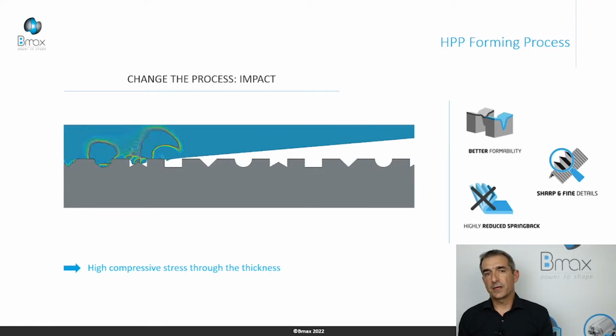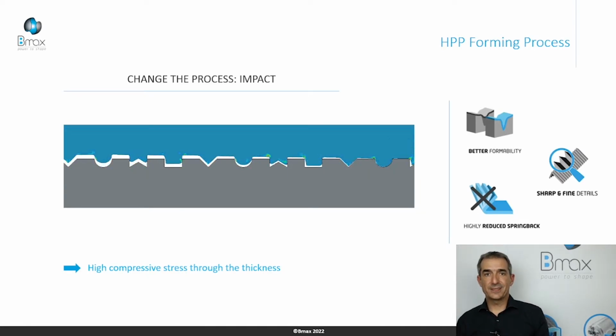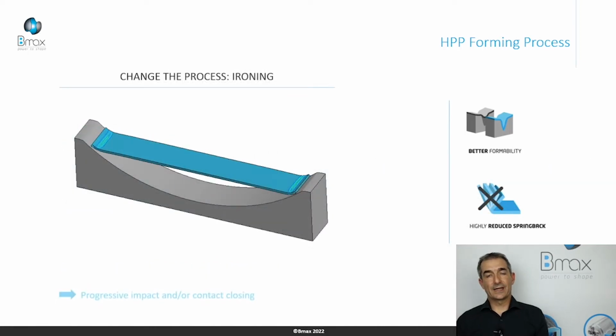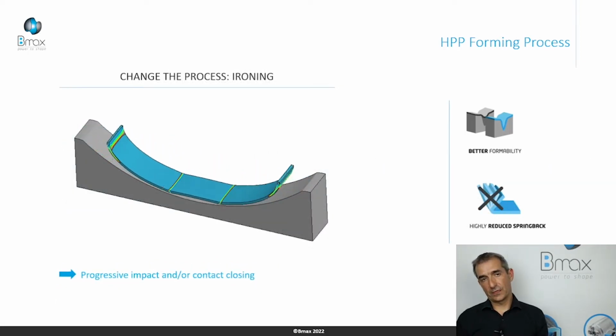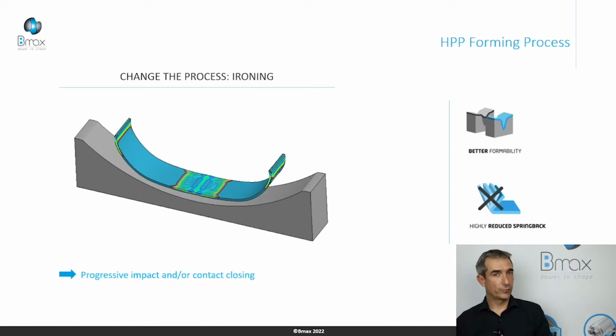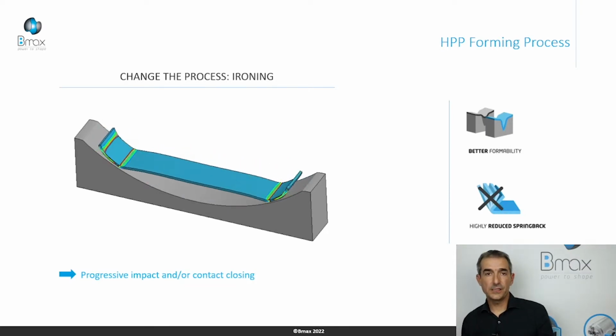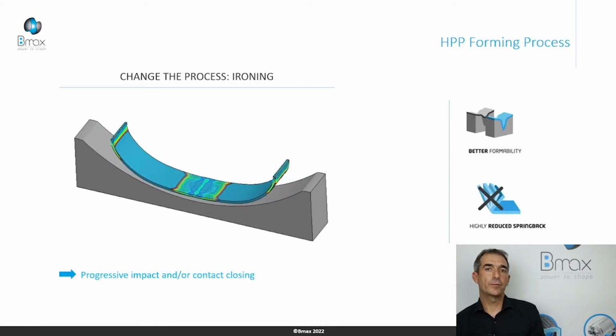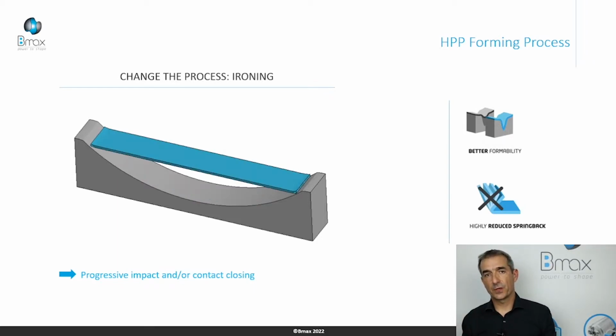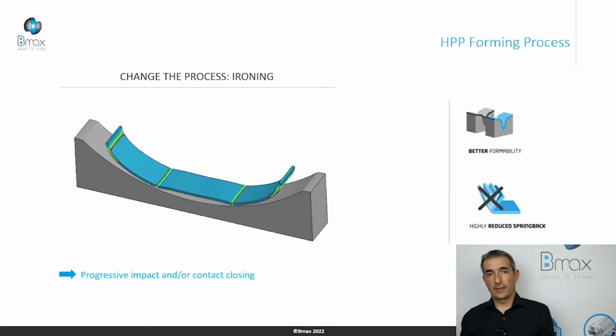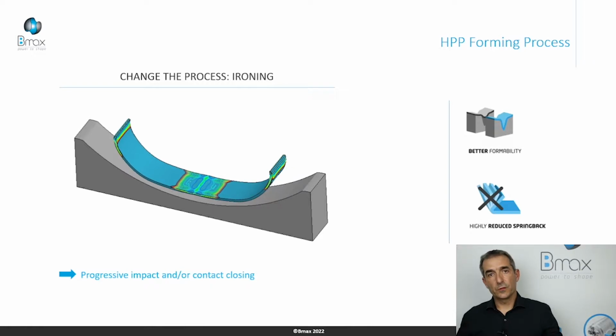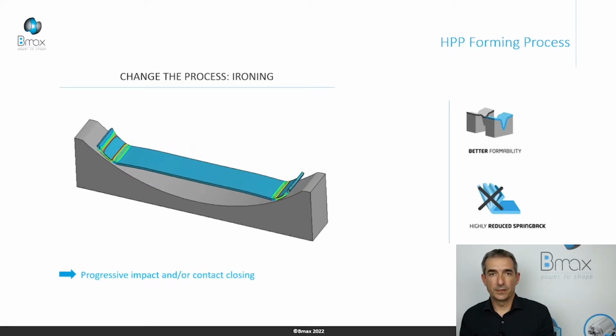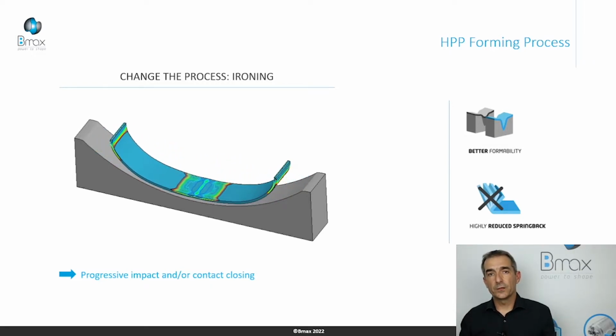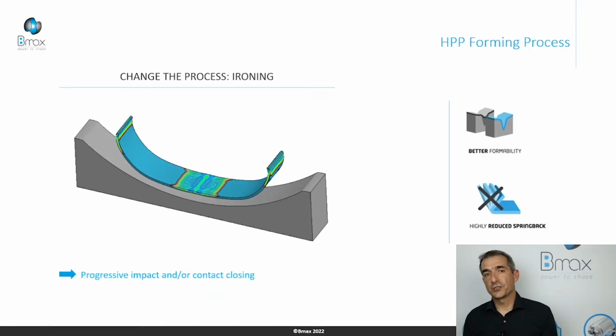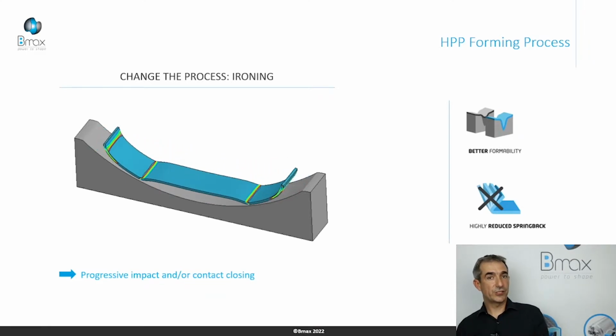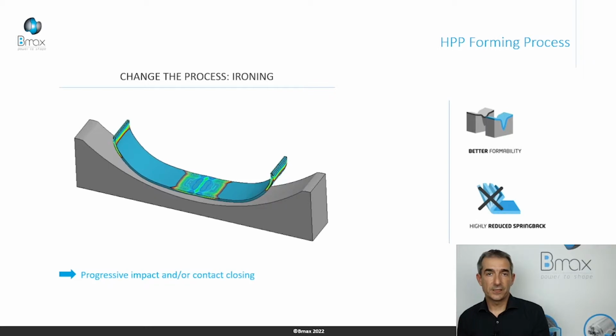But this impact is not constant in time and in space, as usual. So we can have an ironing. Ironing is a progressive contact closing, a progressive impact in a dynamic process. In this example, we have a first impact on the side of the blank, and this contact closing comes from the side to the middle of the blank. In this way, we push the material in the middle of the blank, and we can change the thickness distribution. In this way, we change the formability of the materials.